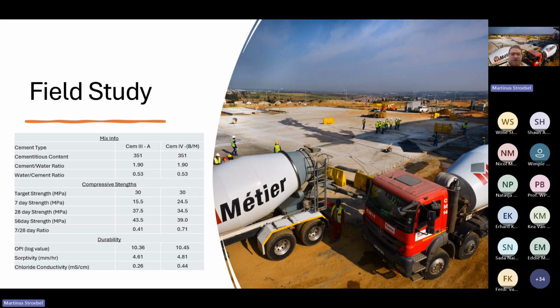And this brings me to my next point, the durability of these two concretes that we compared. If you look at the OPI values, on the slag you got 10.36 versus the fly ash version, 10.45. Both are regarded as excellent values, very good even in terms of the Kotter spec. I'll show another slide of that. This concrete is excellent. In terms of sorptivity, also very similar performance, very dense concrete, it doesn't absorb much. And the interesting fact, which I think most of us know, is that slag is beneficial where you have chloride exposure. The higher the value is, the worse it is in a chloride environment. So achieving the 0.26 versus 0.44 shows that you actually have a superior concrete when you're exposed to chlorides.